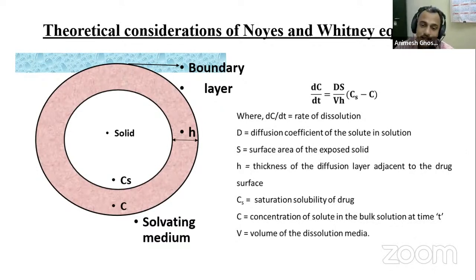So our aim was to reduce the Cs, and how can we reduce it? Saturated solubility generally depends upon the temperature and the solvent. But in a particular solvent at a particular temperature, we can change the saturated solubility by changing its crystal lattice, because it is highly dependent upon the crystal lattice energy of the particular molecule. So if we can change it, the solubility will be reduced, and then dC/dt will be reduced. That is basically the theoretical hypothesis of our work. We have pirfenidone, which is highly soluble. If we reduce its solubility, that means we are reducing its Cs, the saturated solubility. Therefore we can reduce the concentration gradient, and it will definitely lead to a reduced diffusion rate. That is our theoretical consideration.